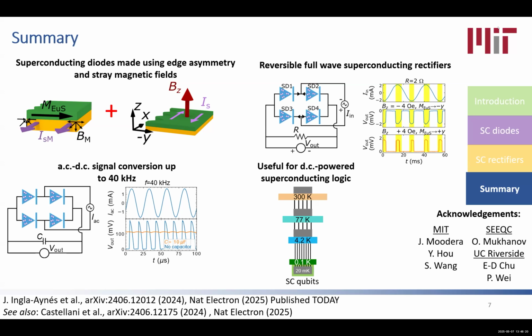It could. It needs to be type 2 to work with this method, but any type 2 will work. Indeed, high TC usually they tend to be type 2, right? Yeah, it's usually a matter of the condition at which you need it to operate. The main thing here maybe is that you don't want to operate at 77 Kelvin because typically wirings and everything that connects down, these are resistive wirings, but usually below 4.2 Kelvin people use niobium and so on. So you can have superconducting interconnects between the different levels. So you may use a high TC superconductor, but you eventually want to use it either at 4.2 Kelvin or below. So the benefit will not be so much unless you want very high critical current for specific high power application.